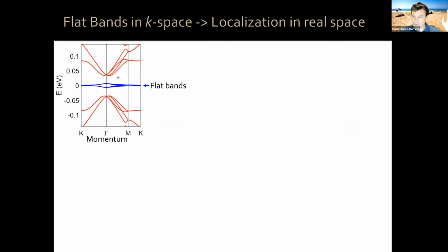Now, let me show you, what you saw before was a cartoon. This is an actual calculation of the electronic structure versus momentum, okay? This is a set of flat bands, okay? And these are the other Moire mini bands, the other remote bands, which result from the folding of the band structure because of the Moire periodicity. These flat bands, as you can see, they're not perfectly flat, okay? But they are orders of magnitude flatter than the original graphene dispersion.